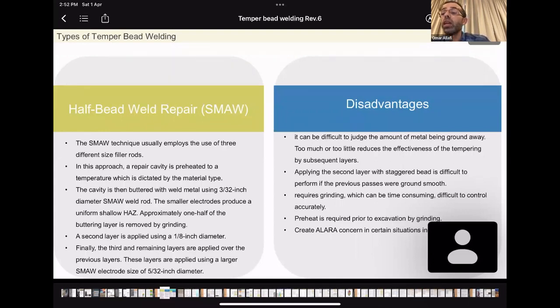Applying the second layer with the staggered bead is difficult to perform if the previous weld pass was ground smooth. So when you do the grinding, it will be ground smooth, and it will be difficult to apply the second layer, and requires grinding, of course, which can be time consuming and difficult to control accurately. Preheat is required prior to excavation by grinding.